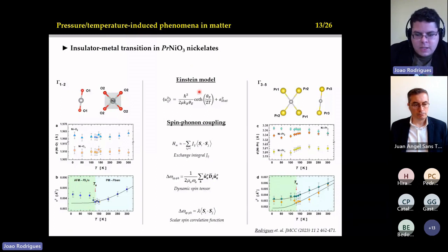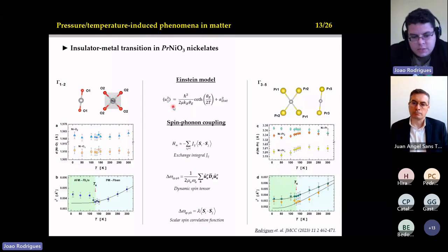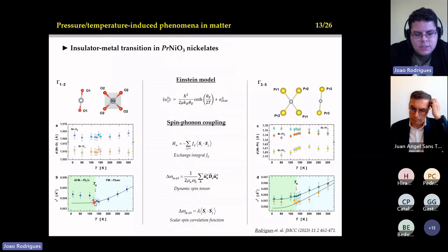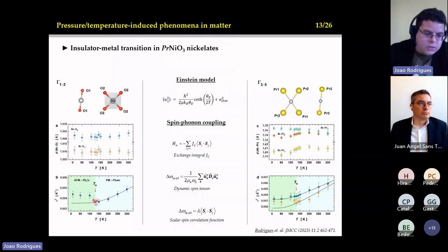Okay. But the very important idea that we have obtained in this work was a special model that we have created with my collaborators at the ESRF, to describe, for example, the departure from the Einstein model when we try to describe the disorder parameter of this material. If you try to describe the disorder parameter of this material, you associate with this disorder parameter a so-called Einstein temperature. This we know from the very basic course in physics. Okay, but this curve here is represented by the black line here, but near the transition we saw that the system does not respect this Einstein model. Okay, so something is happening when we have the magnetic transition.